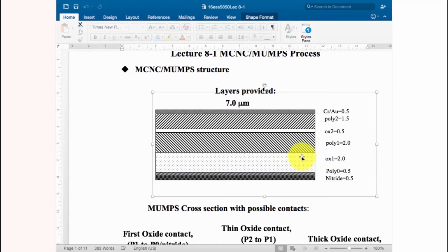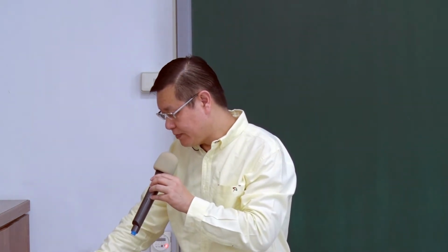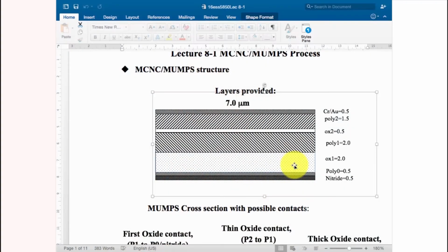The purpose of giving such a thick sacrificial layer is that after releasing, we want to leave some room here if you have some structure that wants to do rotation. If you don't have enough room underneath, you won't be able to do the action of rotation. So 2 micron, I think, is a compromise. If you make it too thick, the deposition process cannot allow you to deposit such a thick material. If you make it too thin, the structure won't be able to rotate. So people found 2 micron may be an acceptable thickness for both the fabrication reason and the functional reason together.